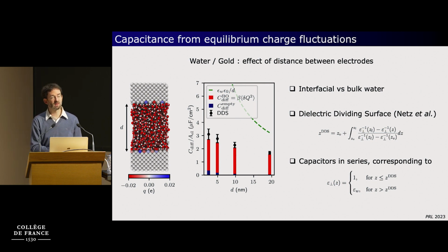And this has to do with the fact that there is a difference between considering bulk and confined water. Not so much that the response of the confined liquid is different, but that there is a subtlety related to how to define the width of the liquid slab here. And in order to do that, you can introduce what Netz and co-workers named the dielectric dividing surface, which you can define from profiles of the permittivity, which I'm not going to describe. And this allows you to map your density and permittivity profiles at the interface into an equivalent sharp interface between vacuum and a bulk liquid.